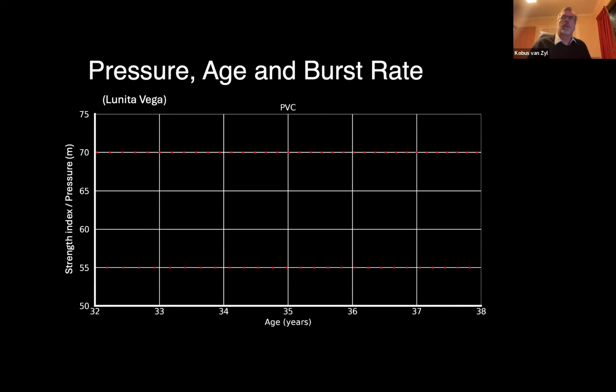And then we said, what we think is happening is that a failure that'll happen at 70 meters will only happen later at 55 meters because it needs more time to deteriorate more. It has to grow to a bigger size, a longer crack, a bigger hole, before it's going to reach the flow rate required to be detectable at 55 meters.